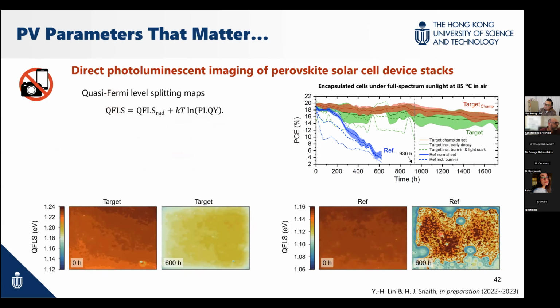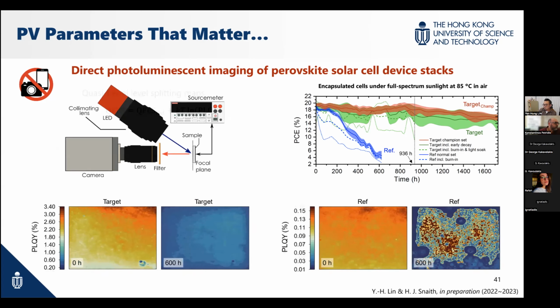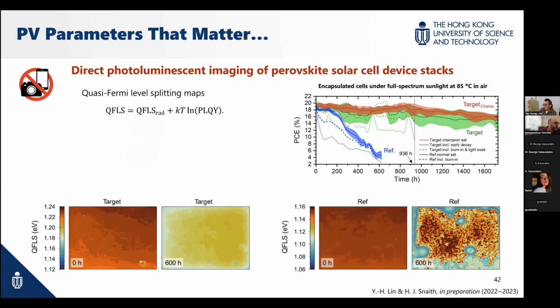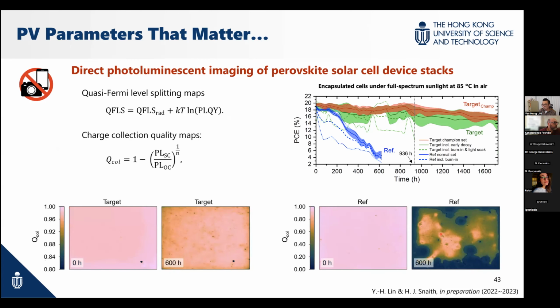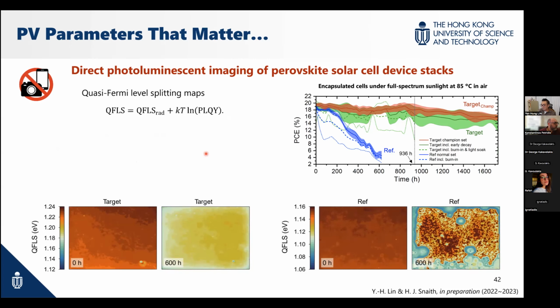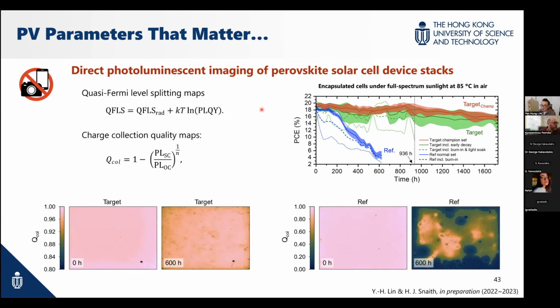But something important is that when we look at the photoluminescence quantum yield, we are only looking at a certain part of the material, because most of the time we are looking at its open circuit conditions. But for a solar cell to operate, we extract charge carriers out of the solar cell, out of the perovskite films. So we did a little bit of modification to this method. Essentially, we look into quasi-Fermi level splitting, and we can easily get this kind of quasi-Fermi level splitting map from PLQY. We also identify another physical property we call collection quality.